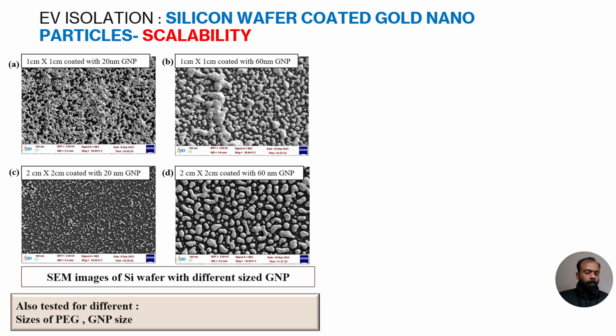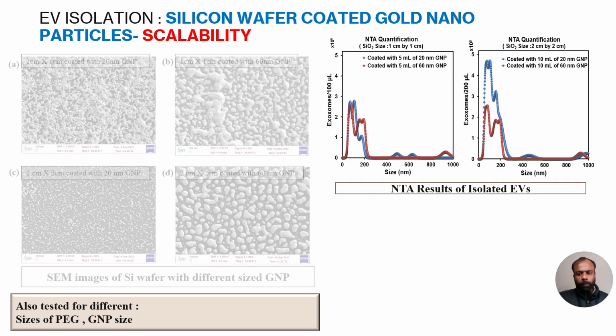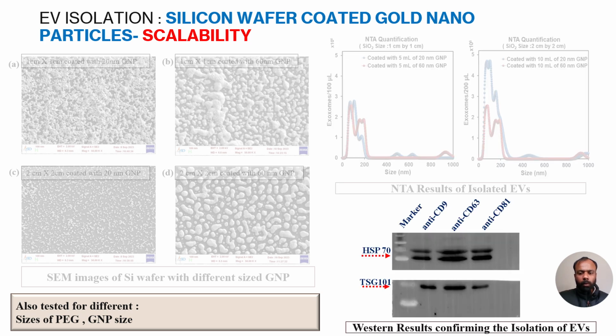The silicon wafer platform was also tested with the different sized gold nanoparticles and polyethylene glycol. And by increasing the size of the platform, we can increase the number of EVs that were isolated. The NTA results are presented here, and the isolated EVs were also tested by Western blotting with different surface proteins corresponding to the extracellular vesicles.